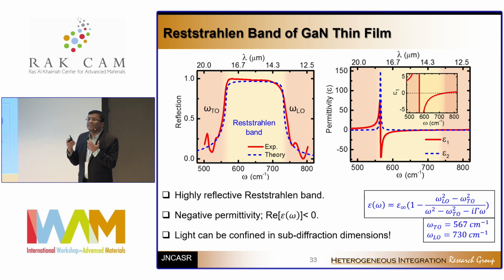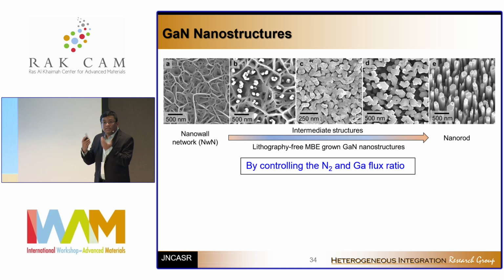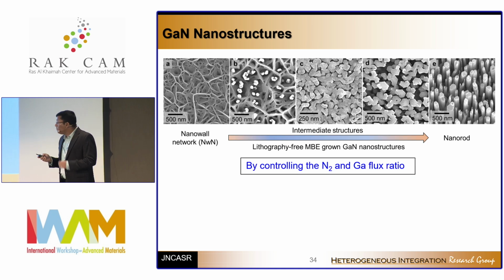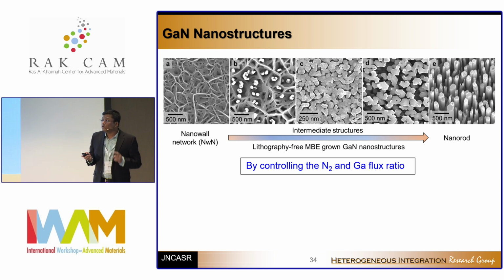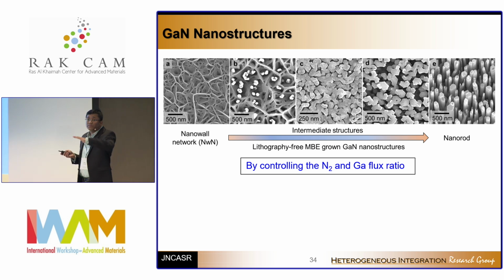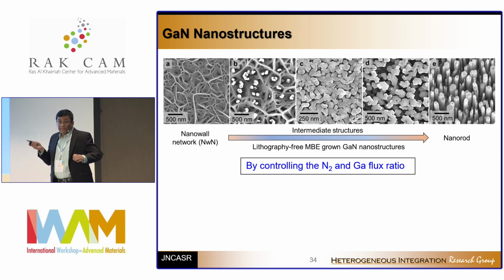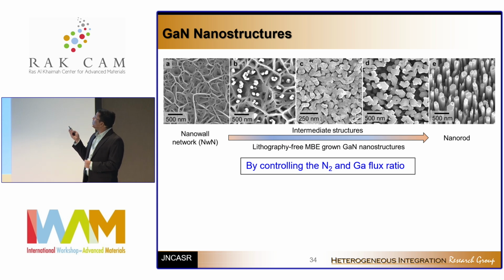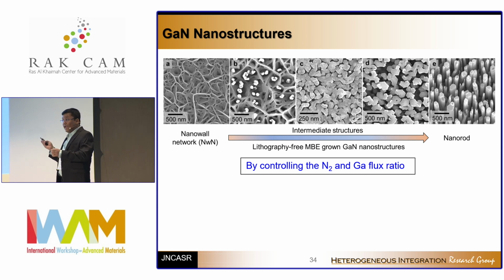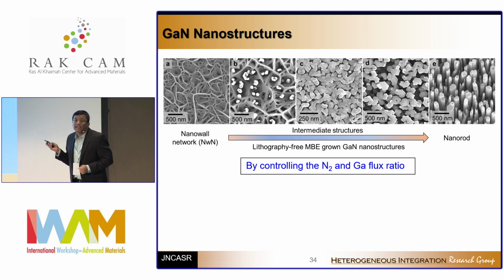As engineers or scientists, we try to find more exciting properties, and the exciting properties that we have developed come from nanostructuring gallium nitride. In our molecular beam epitaxy machine, by changing the growth condition, we can go from thin film to a nano wall network type of growth, like what Professor Jagdish showed yesterday, the nano membrane type. So the membranes are all connected, basically a nano wall network. And if you keep changing the growth condition, in the extreme case, you can also reach gallium nitride nanowires, basically vertically standing gallium nitride nanowires.